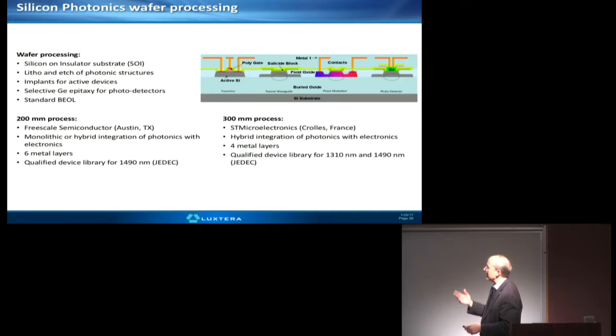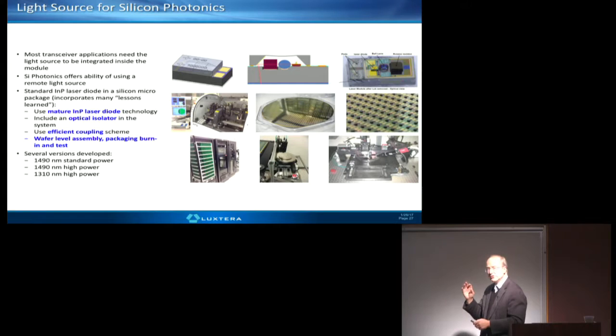This just shows, again, some of the technology. So originally on 200 millimeter, now on 300 millimeter at ST. And this will now transition into the next one. So this is how do you get light into that silicon photonics chip. Right now for AIM, it's a flip chip laser going into a silicon waveguide to a flip chip photonic wafer. In their case, there's a laser sitting up here, and a ball lens, and an isolator, and that couples down to a grating coupler into the silicon photonic structure, and you can see these things here. It works. It's in high volume production, and Eli would argue that the cost of making this package is not significant, and is not the limiting issue.